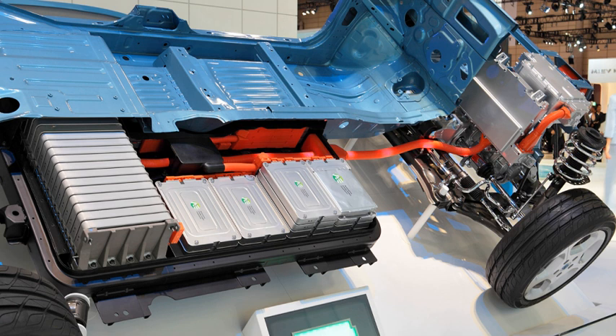Much work is being done on lithium-ion batteries in the lab. Lithium-vanadium oxide has already made its way into the Subaru Prototype G4E, doubling energy density. Silicon nanowires, silicon nanoparticles, and tin nanoparticles promise several times the energy density in the anode, while composite and superlattice cathodes also promise significant density improvements.